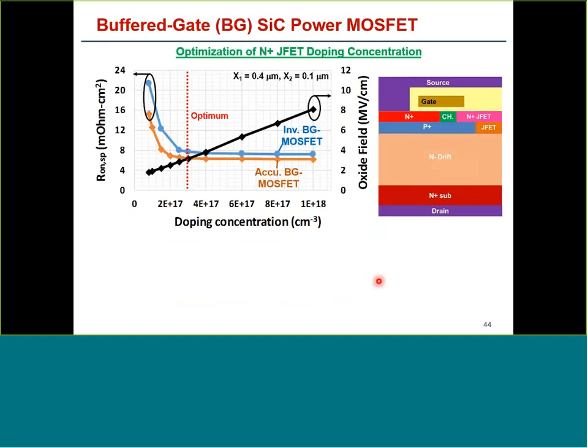So the first optimization we did is to find out the highest JFET doping that we should use, or the right value of JFET doping that we should use. I should mention that if you use too high a JFET doping, then the electric field at this corner goes up and you might end up with bad breakdown.